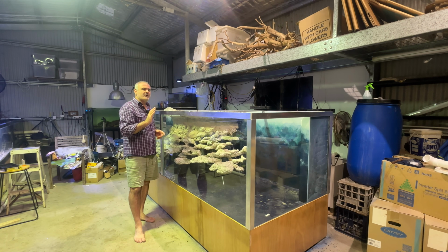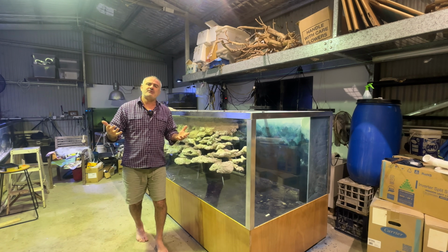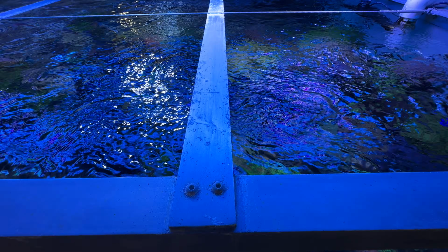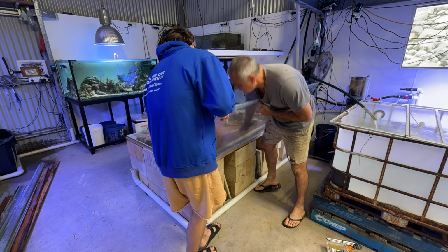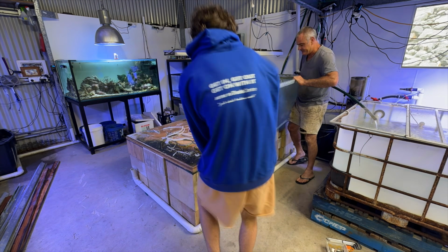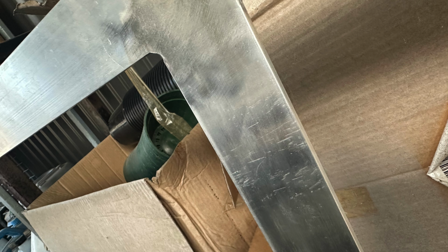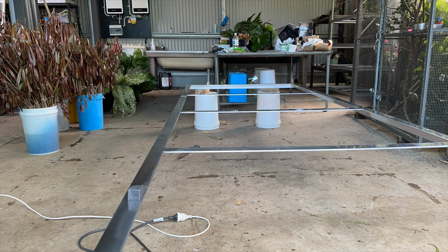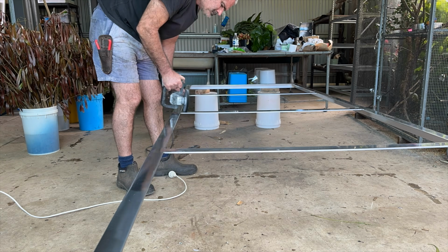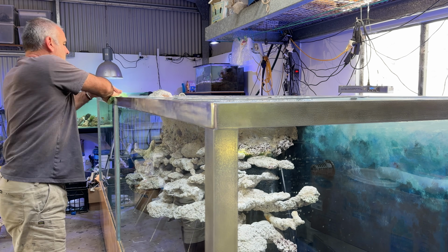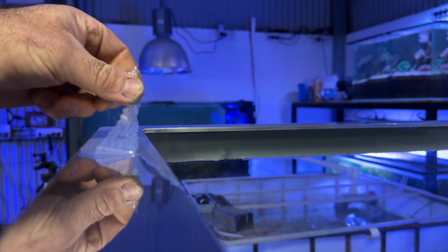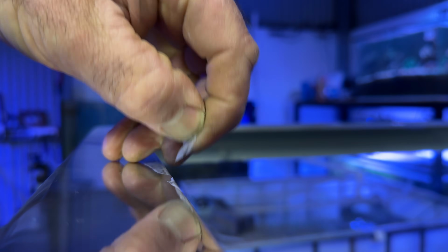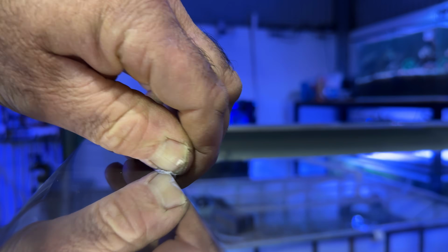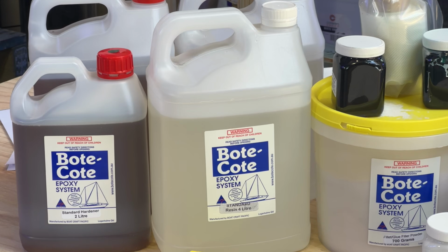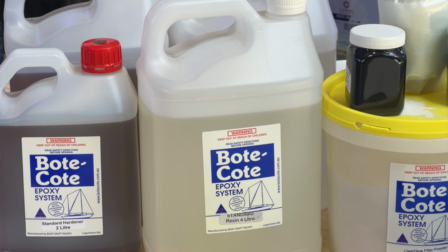In a freshwater style aquarium, aluminium is quite safe to use. But corrosion is a big concern with a marine aquarium, and I have dealt with the white powdery aluminium oxide on my old reef tank. So I decided to go with aluminium. Give it a good polish up, which I must admit was a painfully long procedure, and a thorough clean and seal. So I did try a clear polyurethane sealer, which much to my dismay wasn't successful at sticking fully to the polished aluminium, and so I spent a good long time peeling that old polyurethane off. And now it's back to the good old epoxy coating once again.